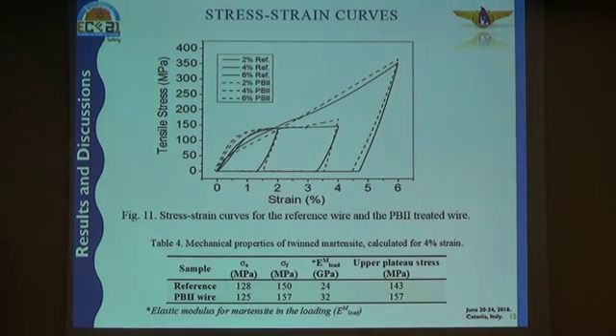These are the stress strain curves that we performed on both wires, reference and treated. In the first cycle, we deformed it up to 2%, and then we heated it to 120 degrees Celsius to recover its shape. In the second cycle, we deformed it up to 4% and recovered it again. And in the third cycle, we deformed it to 6% and recovered. There's a residual strain here. For the reference and the treated wire, if we look at the curve calculated for 4% of strain, we can see that there is a difference in the elastic modulus of the treated wire and the reference wire. But it did not change so much the way that it behaves mechanically.